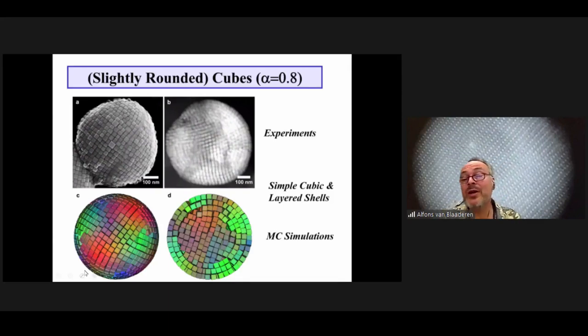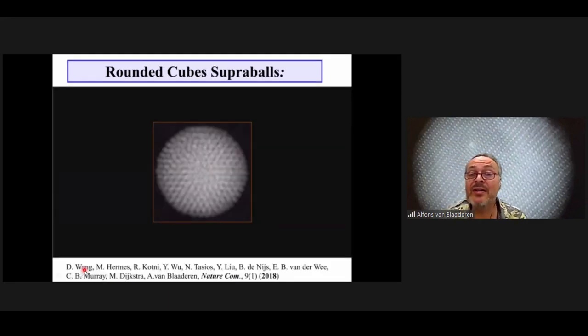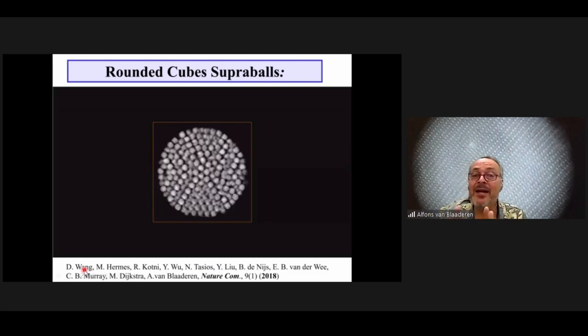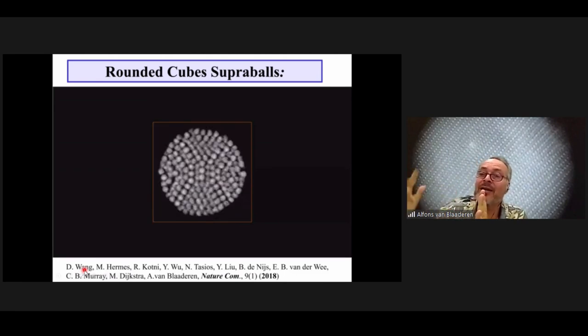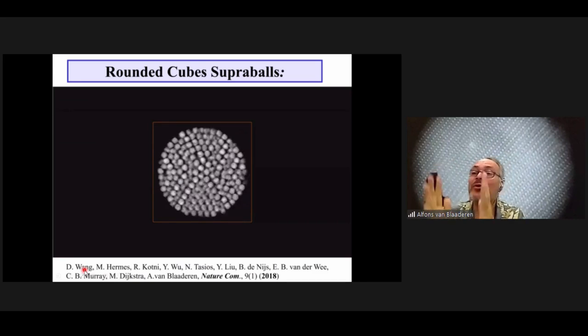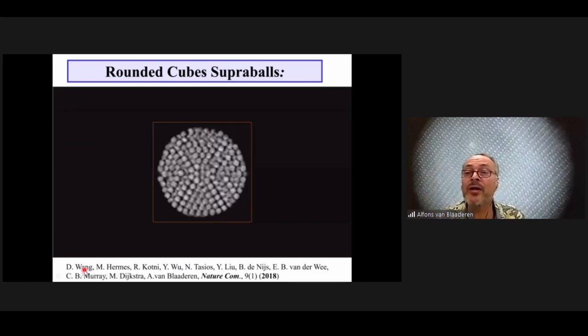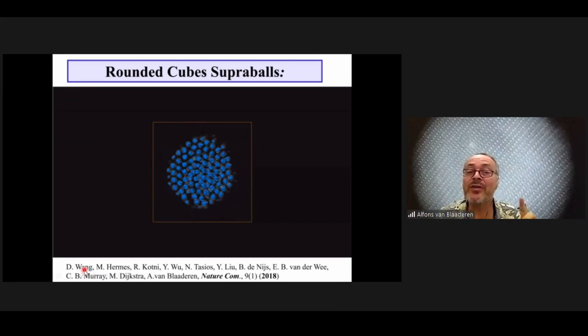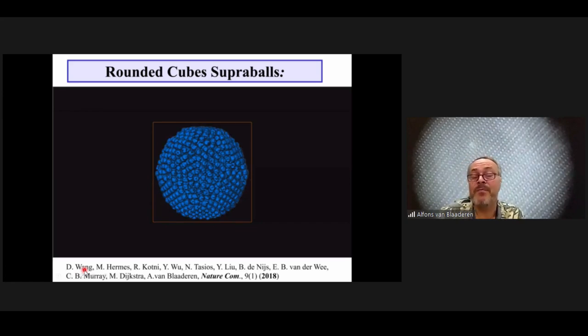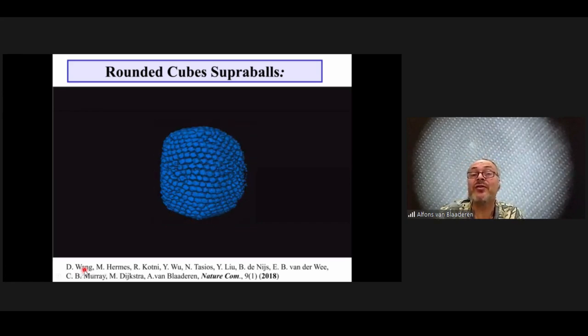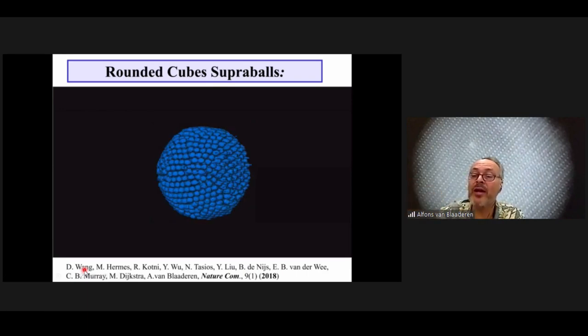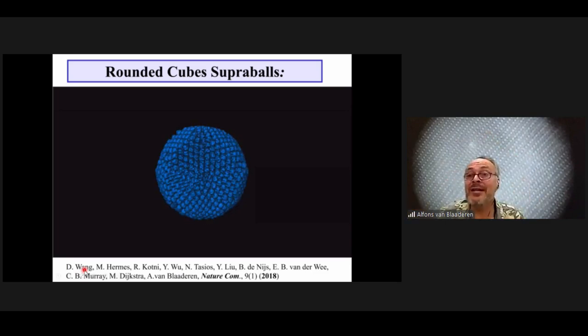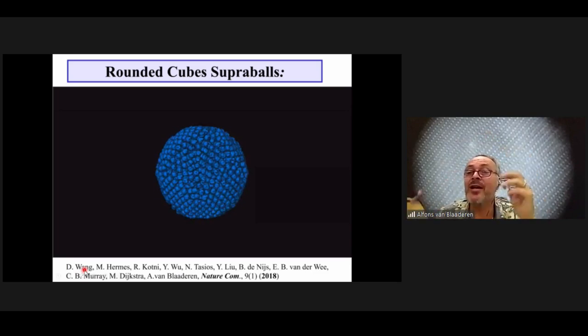However, what we did find is that if you make the shape not completely round, but towards being more round, we went from simple cubic back to this icosahedral structuring. However, with this shape parameter of these superparticles that I'm showing you now, there was still enough flatness that the particles next to them still had the same crystalline orientation of the cube arrangement. So they didn't form simple cubic crystals, but they did form the same crystal orientation as their neighbors. So if we now burn away the ligands and make one crystal of it, it's an icosahedral crystal with holes in it, with a single crystal of the iron oxide.